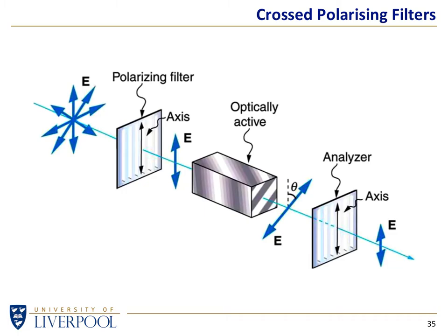But what happens to the light that comes through is when we go through a piece of sellotape, just like a lot of rocks, it is what we call optically active. It will change the orientation of the polarization. In other words, any light which is coming through, let's say, the vertical, before it goes through the horizontal, the sellotape or the rock sample is changing the polarization. The light is coming through vertical, but the sellotape or the rock is actually changing it so that some of that light will make it through the next polarizer, which would be horizontal in this particular case.